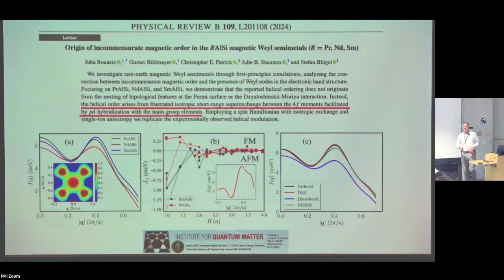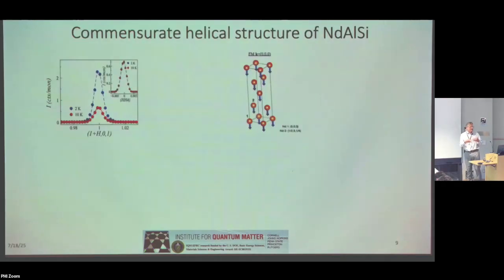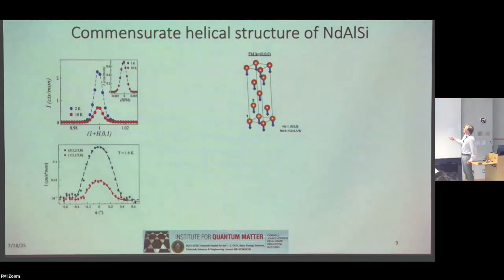And so it was an interesting result. And so we dug a little bit deeper into the nature of the underlying structure to understand how we could make proper connections to the Weyl nature of the electronic band structure. I want to say that this spin structure in the incommensurate phase actually has several different components that are kind of superimposed on each other. So this is the commensurate antiferromagnetic peak, which indicates the presence of a ferromagnetic component. Sorry, this is in the commensurate phase.